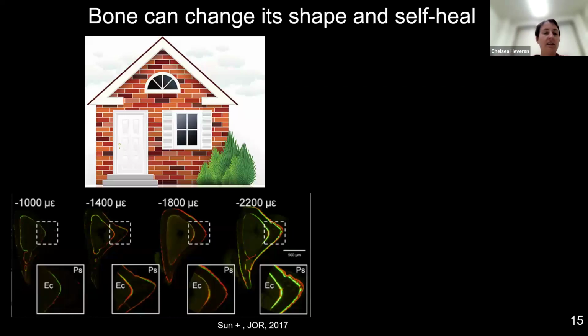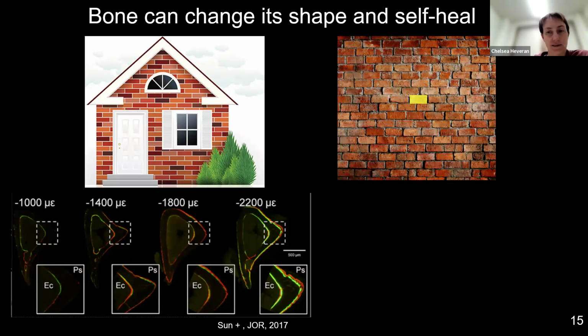What you're looking at here, these are cross sections of a tibia from a mouse. And the labels, the green and the red, are fluorescent dye that was injected into the animal. And what you're seeing here, this negative 1,000 microstrain up to negative 2,200 microstrain, this is from intentionally loading the tibia. So the negative 2,200 is a big enough strain on that tibia on the live animal to cause the bone to grow. So the green and the red show you where the bone is growing. It is adapting to an increased load. That's possible because bone is filled with cells.